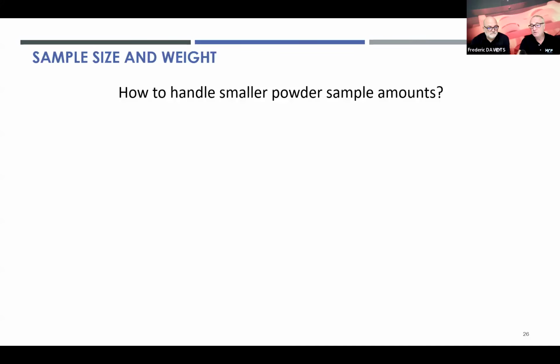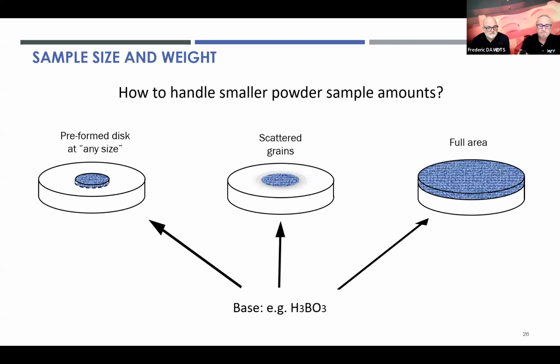So we can also have just maybe smaller amounts of sample. And if you just have a small amount, maybe 1 gram or less than 1 gram, there are different ways to prepare those samples. We can always take as a base, and that's the white part here, a boric acid tablet. And then we can put our sample on the surface. So this can be a preformed boric acid, or this can just be a plain boric acid tablet on which we scatter some grains, or this can be a plain boric acid disc on which we can still add a couple of millimeters of sample, depending on the quantity of sample that we have.